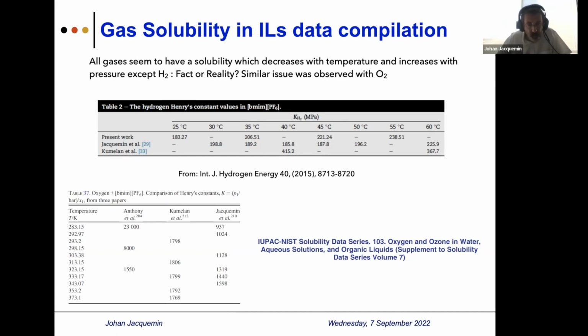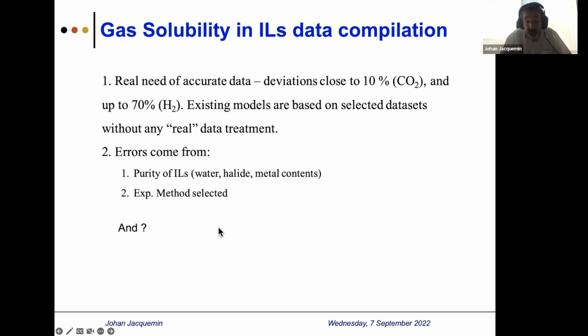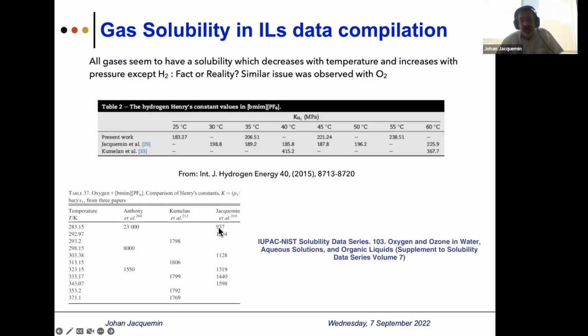And as you can see, the data moved from 23,000 measured by quartz microbalance, and moved up to 937 measured by volumetric techniques. And of course, the group of Maurer in Germany say, well, there is no change in solubility. However, no extra data has been published so far to argue on oxygen solubility.